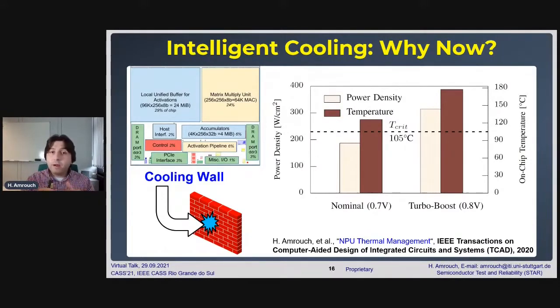And what we have observed is that the temperature of the systolic array will go beyond the critical temperature of 105 degrees. At the nominal voltage of 0.7, the temperature will reach above 120 degrees, which is indeed critical. And whenever we boost the voltage a little bit and go to 0.8 volt, the temperature of the systolic array will even exceed 130 and 140 degrees.